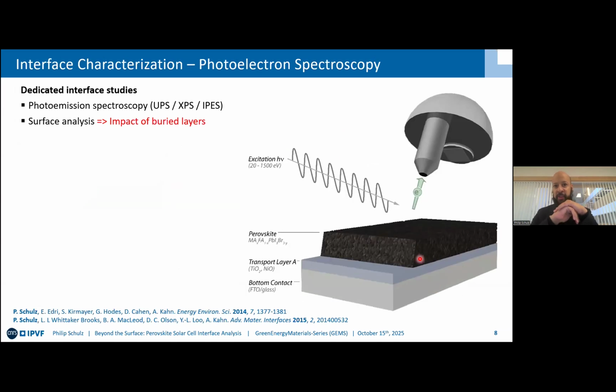And speaking of photoemissions, photoelectron spectroscopy, to be a bit more technical about it, this is the tool that has been established over the last decades for dedicated interface studies for semiconductor devices in general. You can roughly split it into ultraviolet photoemission spectroscopy (UPS) if you use UV light in order to excite photoelectrons, XPS, or X-ray induced photoemission spectroscopy, when you use X-rays. And again, for the sake of completeness, I also added IPES, so inverse photoemission spectroscopy, that allows you to look into the unoccupied states, whereas the other two are, of course, probing the valence band and also the core levels.